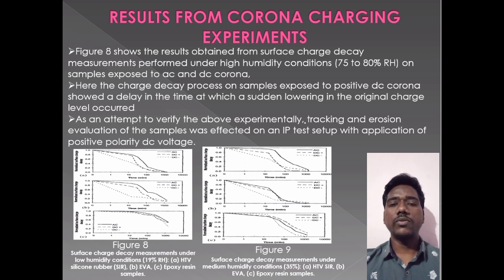For both RH values, longer decay times were observed on samples charged with AC and positive polarity DC. This trend can be identified easily in HTV, SIR, and EVA samples. Nevertheless, under these humidity conditions, the longest decay time corresponded to epoxy resin compound, which may be attributed to the more polar nature of the polymer as compared to HTV, SIR, rubber, and EVA.